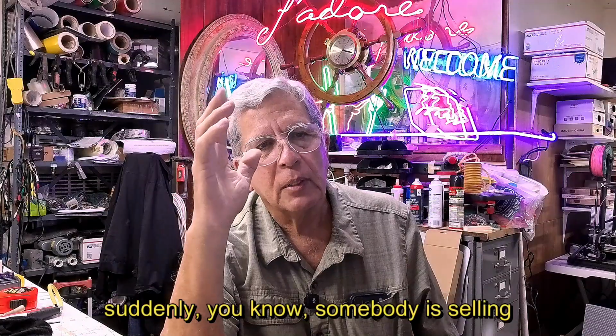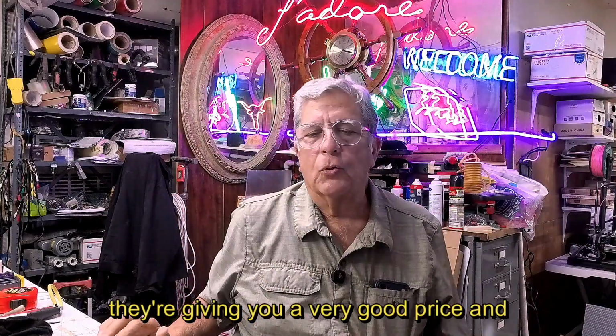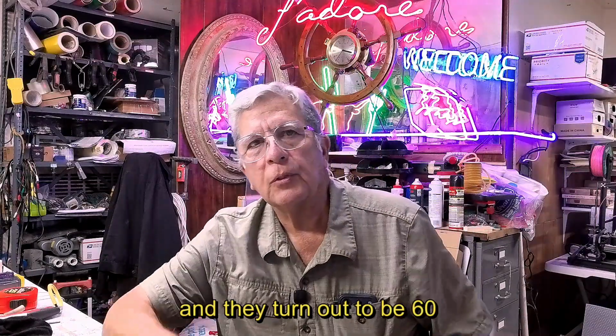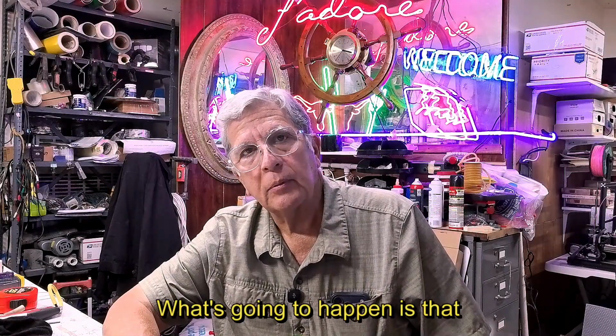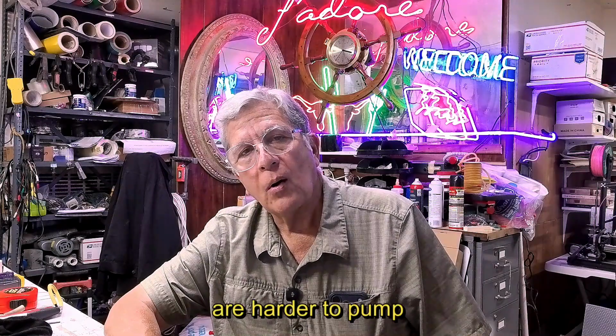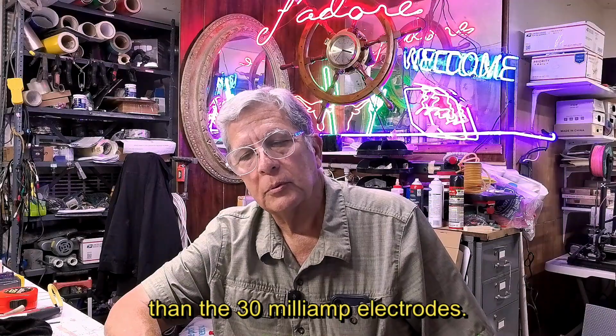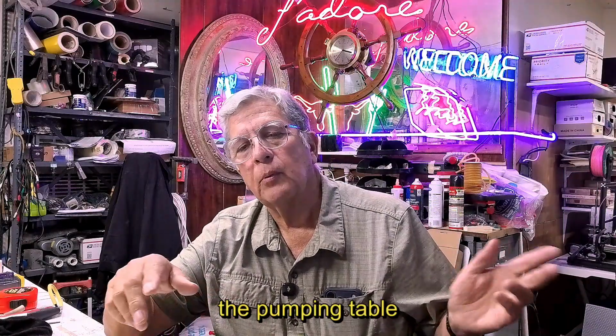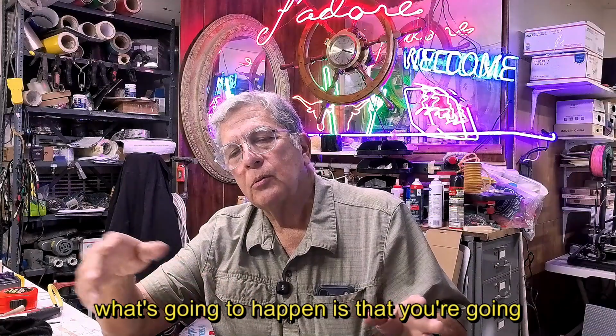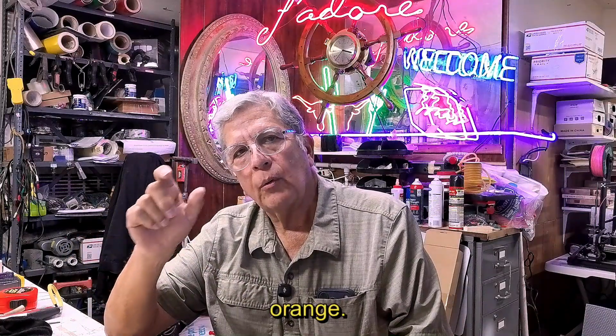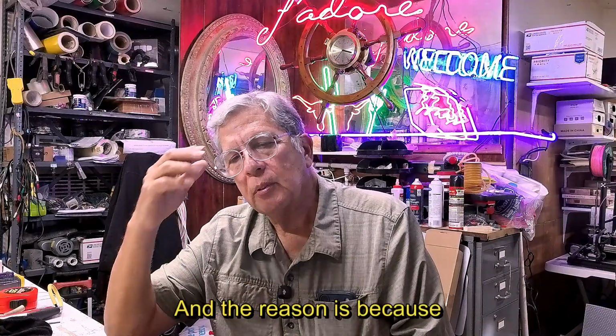But you can come across, suddenly, somebody is selling electrodes and they're giving you a very good price and everything, and they turn out to be 60 milliamp electrodes. What's going to happen is that those 60 milliamp electrodes are harder to pump than the 30 milliamp electrodes. So you'll be pumping it on the pumping table, and you're going to see that those electrodes don't get orange. No matter what you do, they don't get orange. And the reason is because they're tougher to pump. Eventually they will go orange, but you don't need to.